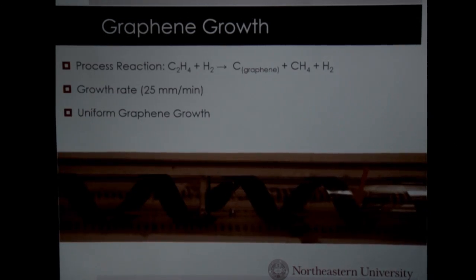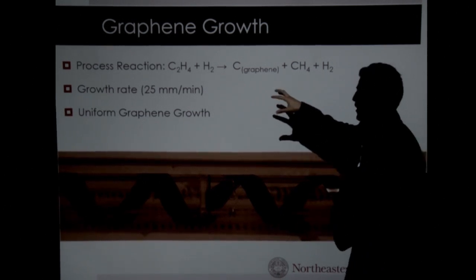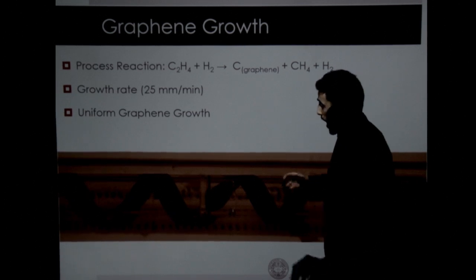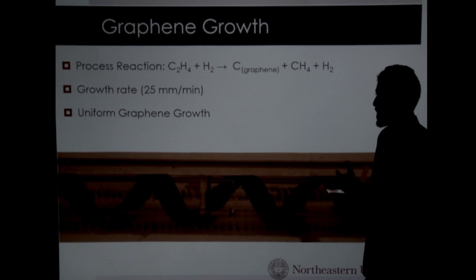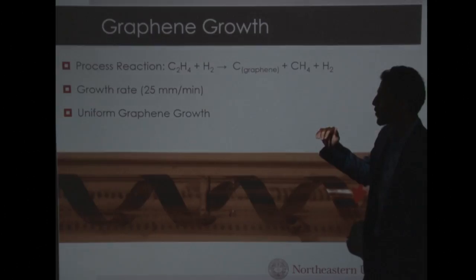And this is the reaction that takes place in the CVD reactor, which is the ethylene reacts with the hydrogen to get the graphene and the methane gas and the hydrogen. And the growth rate of this graphene layer forming on the copper foil was found to be 25 millimeter per minute. And this growth rate was found to be the optimal growth rate for a uniform graphene.